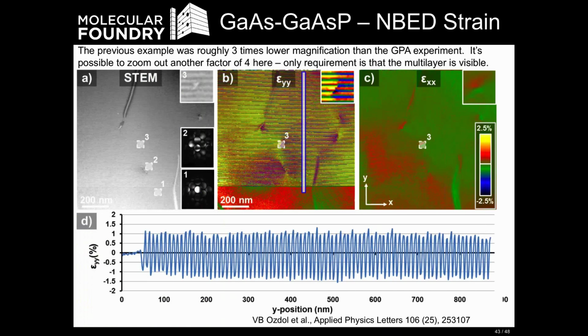If there's a defect, for example, a dislocation, you can see a couple of them in this panel in A, we can still get the local strain field everywhere around it, as long as we can still see at least two diffracted disks that are perpendicular to each other. So in B and C, we can now see the perpendicular and parallel strain fields again, but in the presence of defects. And as you can imagine, this is definitely very, very important because a lot of these devices, the performance is limited by the most defected regions, not by the most perfectly grown regions.